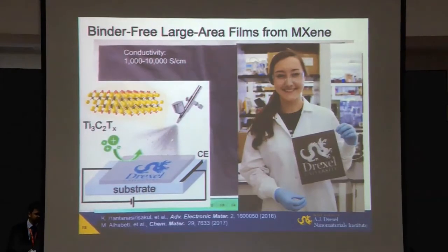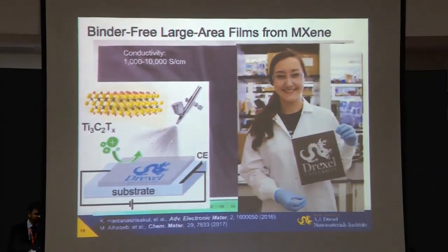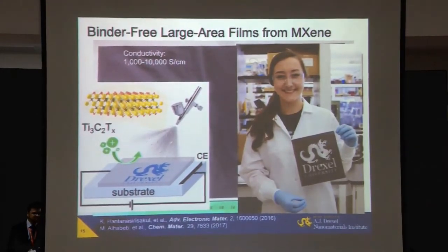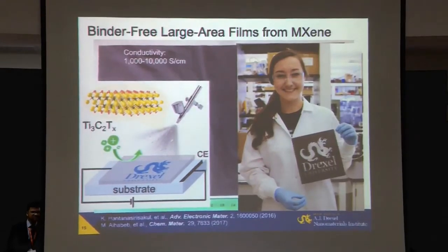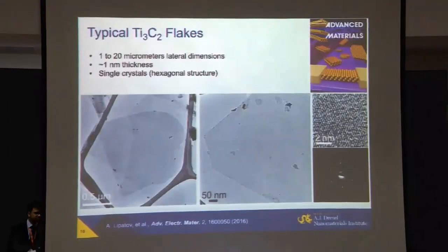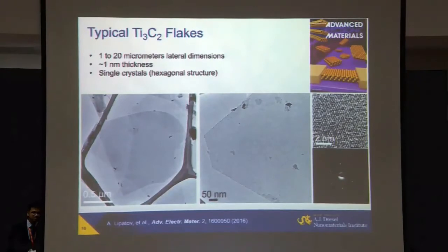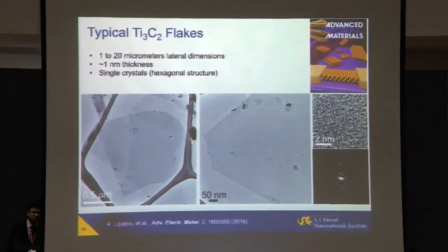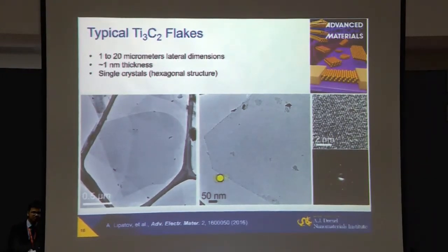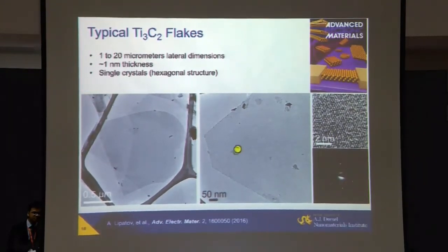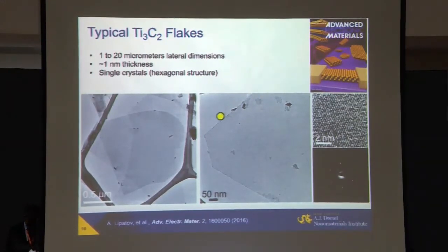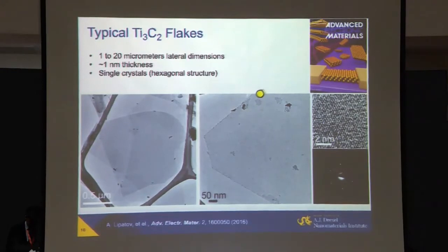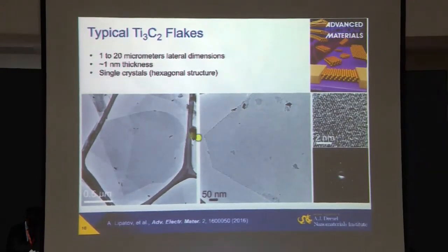And this again shows that you don't need some kind of super sophisticated equipment to do novel work and make novel materials here. But if you take a sophisticated, more expensive piece of equipment like an electron microscope, and look inside, what you see, you will find flakes like this one, several microns in size, and this one follows actually hexagonal symmetry of the precursor phase, MAX phase, and those are monolayers of MXene laying here.